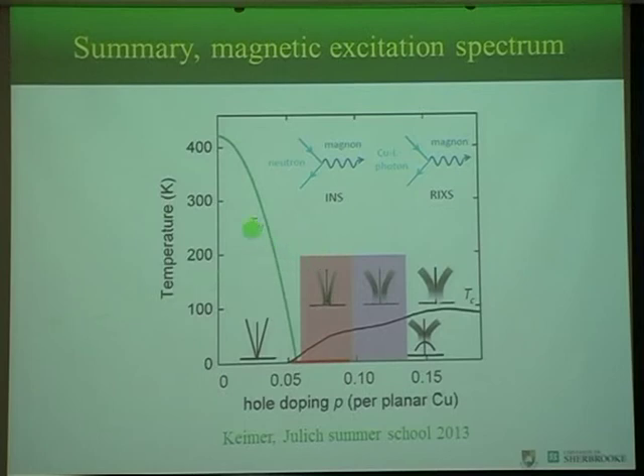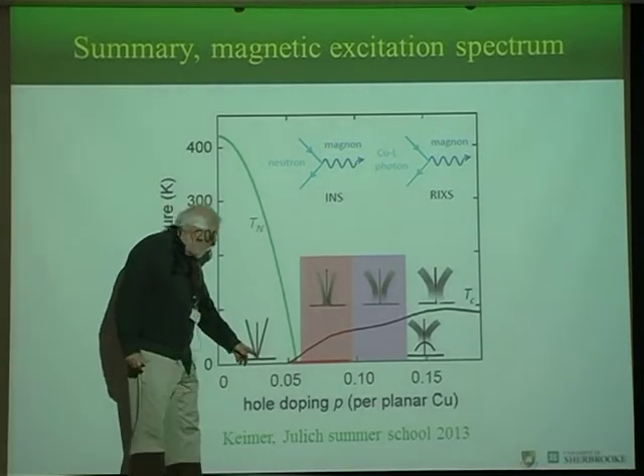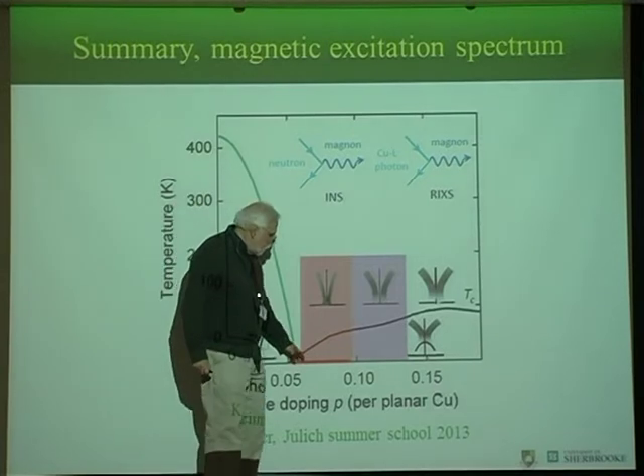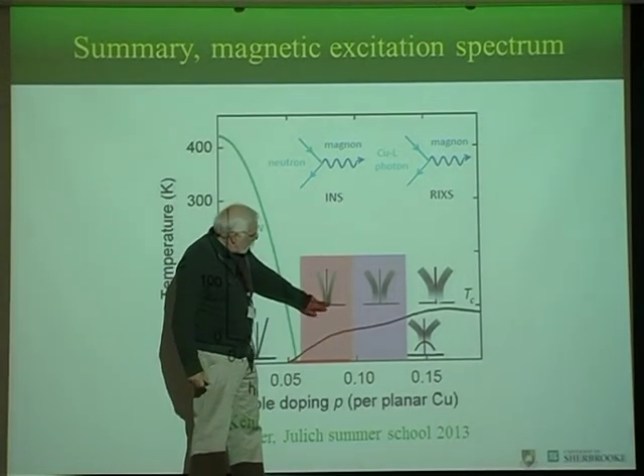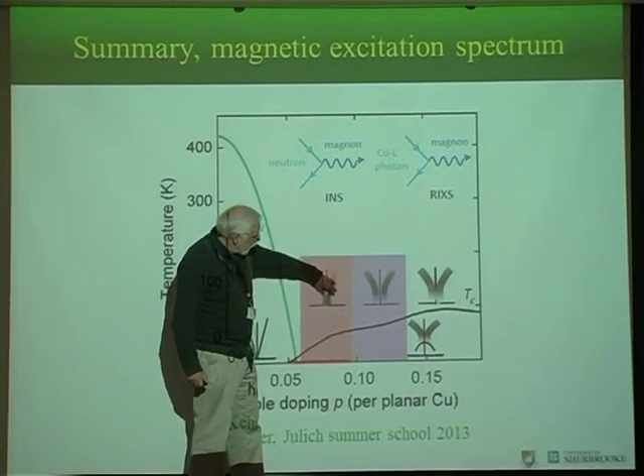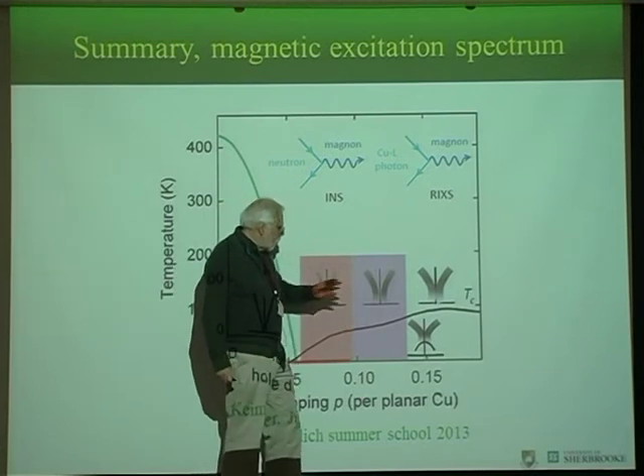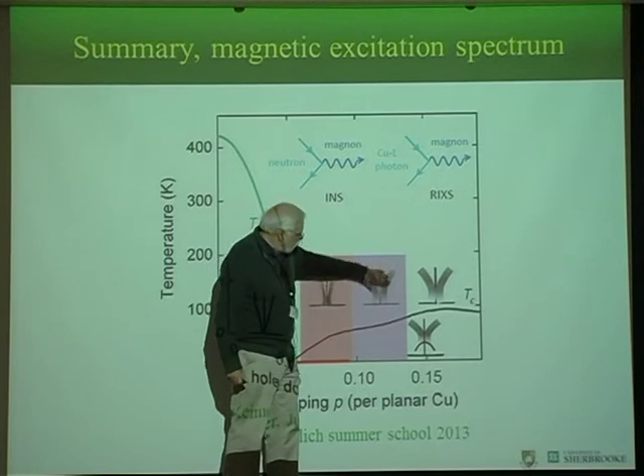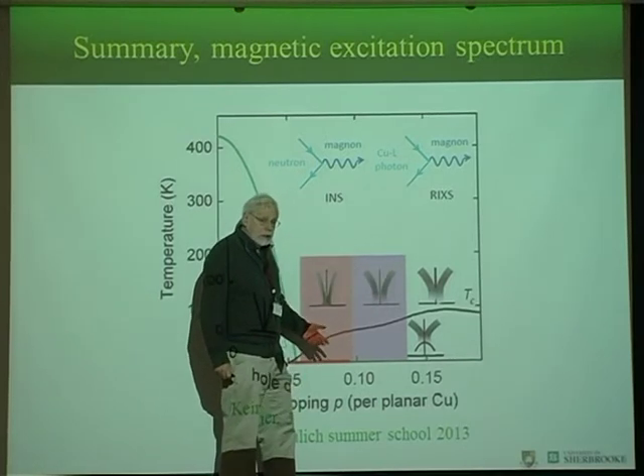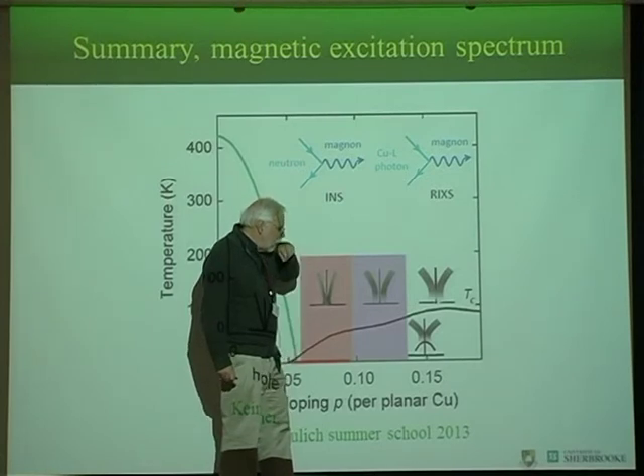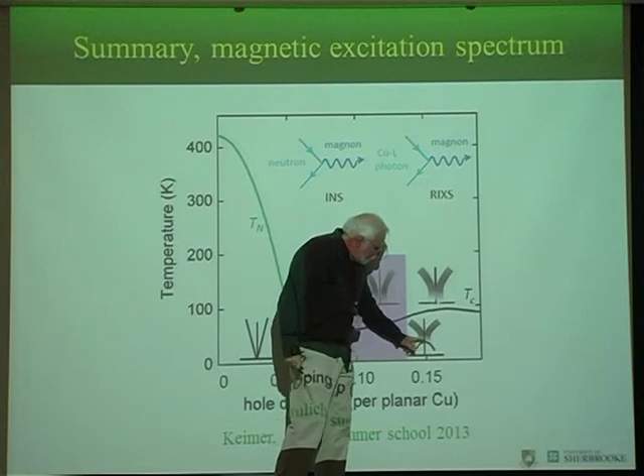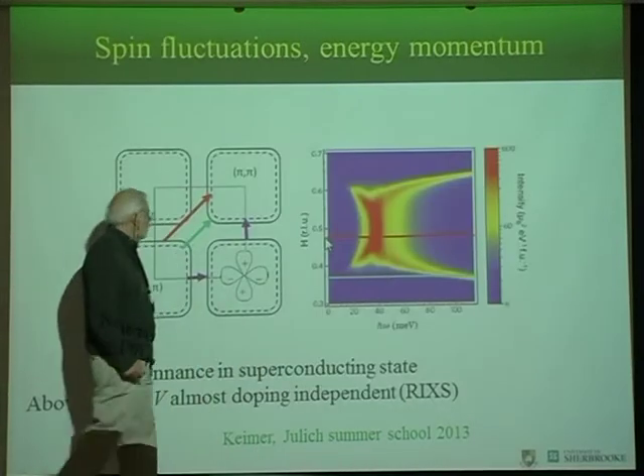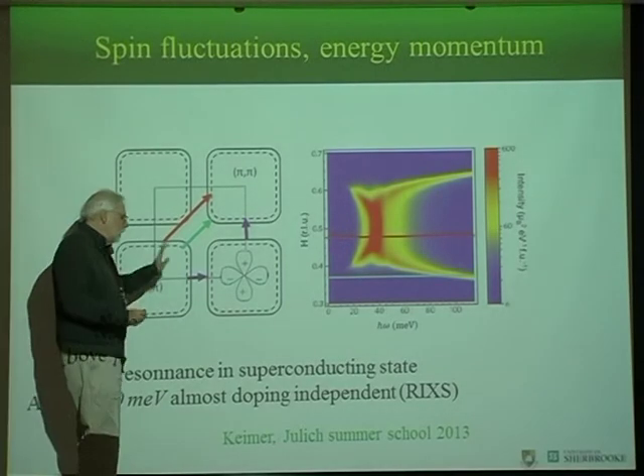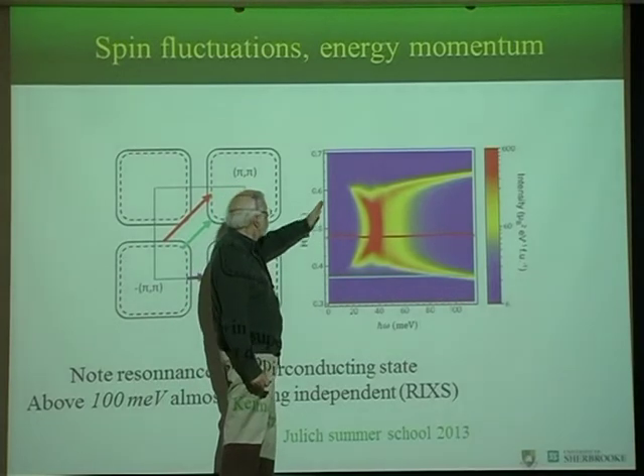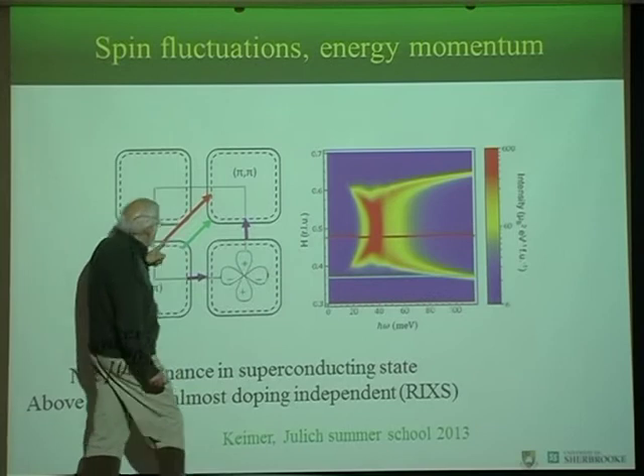Okay, so in the hole doped cuprates, this is what I just showed here. In the antiferromagnet, or the lightly doped antiferromagnet, you get well-defined spin waves. Here, you are in a regime where they are incommensurate. In other words, they're not quite at pi, and they have this hourglass shape. In this region, we'll talk about it later, there's a charge density wave, but there are still some relatively well-defined spin excitations at high frequency. In the superconducting state, there's a resonance that appears here that I will show you on the next slide. So it's a busy slide, and it's not really so important for our discussion, so I won't spend too much time. But we are scanning this way here.